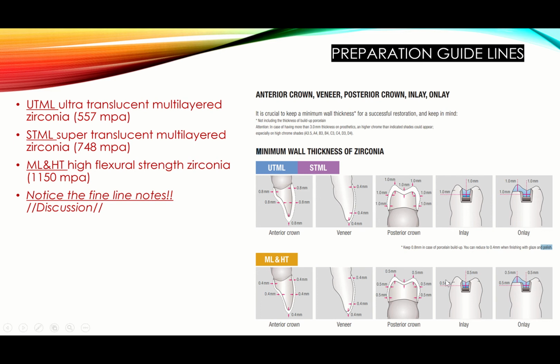Now over here they tell you yes, you can go 0.5 millimeters all around for a posterior crown, but using the high flexural strength zirconia. You're only talking about HT or ML from Katana, or you're talking about Prettau that can give you the 0.5 millimeter, and I think that you are on the edge. You're risking too much by going 0.5 millimeter. Now Prettau, we know that it's very hard, it's very strong, and you know they say that you can use 0.5 millimeter in the posterior area. I just mark my objection on that.